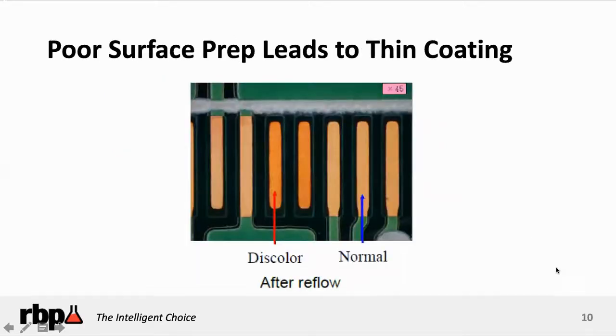Here's a good example again. Oftentimes we have non-uniform thicknesses or dirty surfaces that minimize how the OSP coats and forms. Again, the arrow is pointing to a discolored area here. This is oxidation. The other pads, the fingers, seem to be looking really good. Again, this is a surface preparation situation. Something was left on the surface, not cleaned properly, and it was affecting how well the OSP film coated.